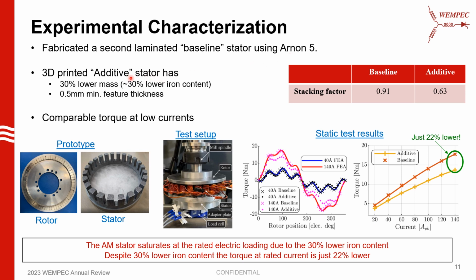The 3D printed additive stator has 30% lower mass, which translates to 30% lower iron content compared to the laminated baseline stator. So we would expect approximately 30% lower torque at the rated current with the 3D printed stator. The lower iron content is primarily due to the air regions within the Hilbert structure and the 0.5 mm minimum feature thickness required by the additive manufacturing equipment capability.